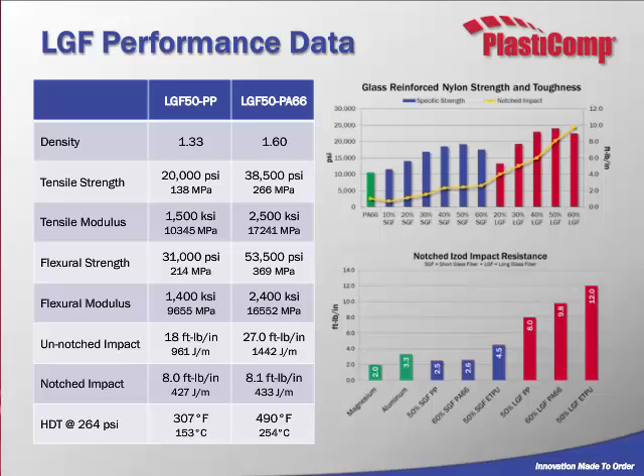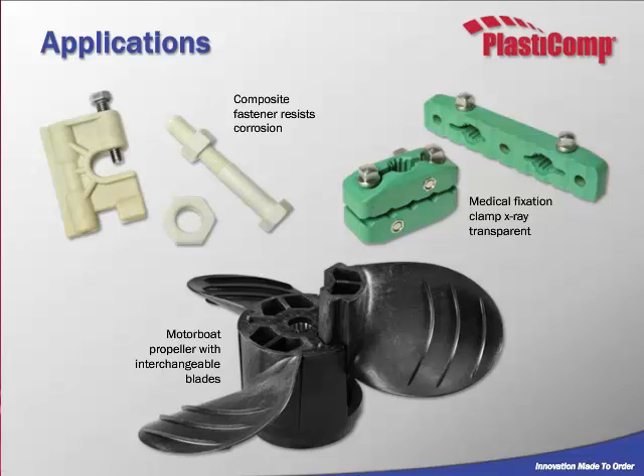On the bottom, a similar slide comparing some different materials to magnesium and aluminum. So again, a clear winner there with the long fiber materials. Now I mentioned earlier the nuts and bolts that are produced using our material. There's a shot of those, and when we burn those off, those threads are filled out with our fibers. So again, the misnomer that our materials are not going to fill out real intricate areas is false. We've got the medical clamps that I mentioned that had the radiolucency, as well as a very durable part for a very demanding application, and that's where some of our maximum toughness formulas come into play with the boat prop. You can imagine the abuse that this type of product would take, and that's where our maximum toughness grades come in.